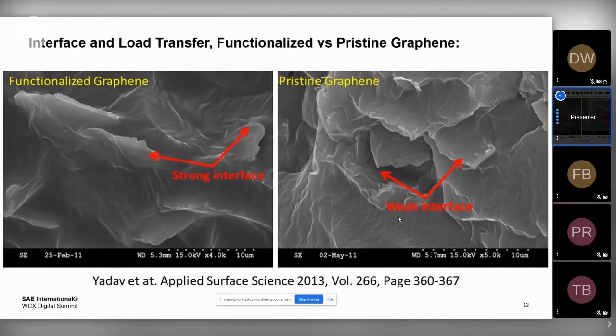Back in 2013, Santosh Yadav and others at Konkuk University in Seoul, South Korea, did a study where they tried to study the difference between what we would call functionalized grafting, where they applied polymeric modification to the surface, versus pristine grafting that they didn't, and they compounded it into a urethane composite. What they found through SEM microscopy was that if they had functionalized the graphene to be appropriate for the material they're working with, they achieved a very strong interface between the polymer and the surface of the edge of the graphene, which you can make out in this SEM micrograph on the left. On the right-hand side, a weak interface shows that you actually have fracturing, which results in the polymer pulling away from the surface of the graphene, and that tends to result in weak properties.